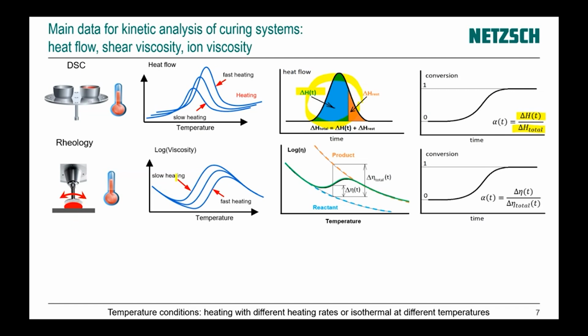Another measurement is rheology, for example, an oscillating rheometer. Here we have the log of shear viscosity. Again, we can make slow heating and fast heating. We have the same baseline before and after measurement, and different curves during the heating. Then for each curve, we can create a baseline for the reactant and a baseline for the product, and create the ratio between the current change of the log of viscosity and the total change of viscosity, as the difference between the viscosity of product and viscosity of reactant. And now we have a degree of conversion.